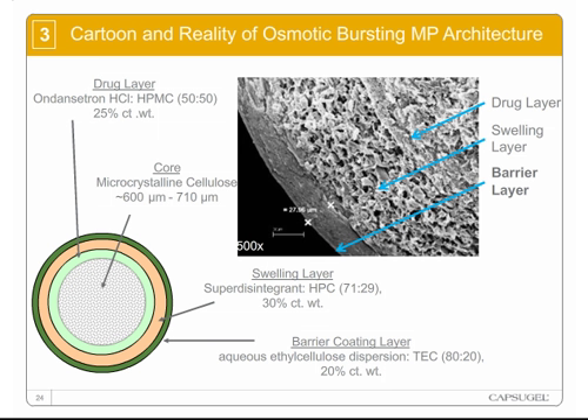The swelling layer is the next layer going from the inside out, and it's key to the mechanism of release. As water permeates the upper layers, this swelling layer starts to apply physical pressure on the barrier coating layer above it and effectively bursts it at a very prescribed time, as you'll see in the next couple of slides. The barrier coating layer is the final layer, and it does allow water to infuse into the particle, and this barrier coating thickness and strength is key to tuning the lag time of any formulation. Overall, the size of these particles does have some effect on the release parameters that need to be achieved for any particular product.